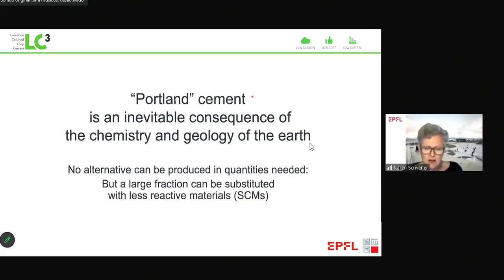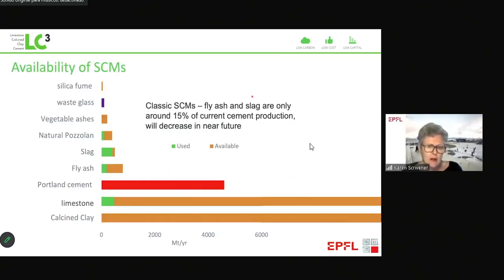technology, is replace a large fraction of this with other materials which are called supplementary cementitious materials. The problem is that the supplementary cementitious materials we've been using mostly to date are things like fly ash and slag. And there's two problems there. First of all, even today, the amounts of these materials is really limited. Together, they probably only make up about 15% of current cement demand. But the second thing is they both come from very carbon-intensive processes.